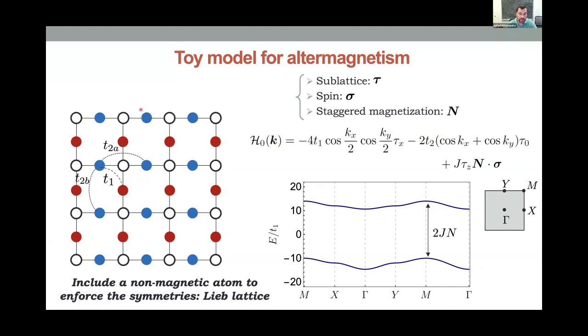The easiest way to do that, at least in my opinion, is to include these non-magnetic atoms that I'm putting here. And when you do that, you immediately realize that these 2 next nearest neighbor hoppings have to be different. This one goes through a non-magnetic atom, and this one doesn't. I'm going to call this difference TD, and you can see that this is nothing but a realization of the Lieb lattice. If you work on cuprates, you immediately recognize the Emery model, but it's kind of inverse because we're interested in the oxygen and having the copper bands, if you wish, be high energy.